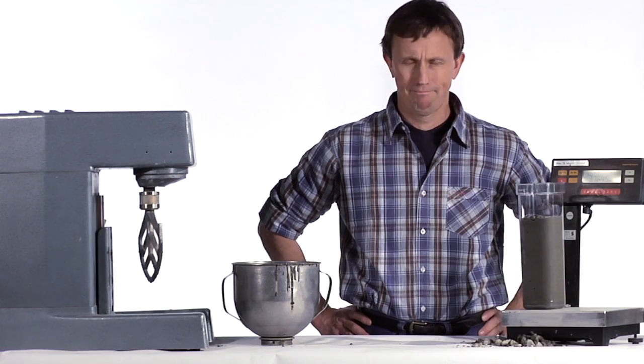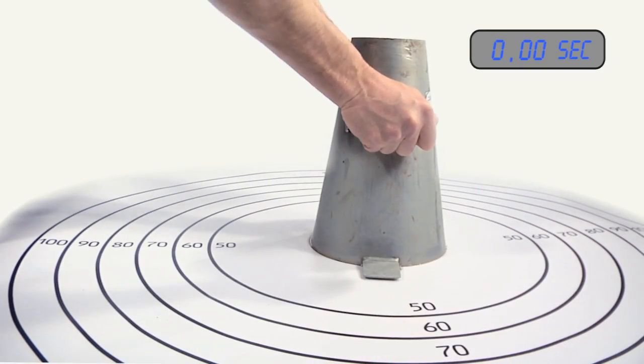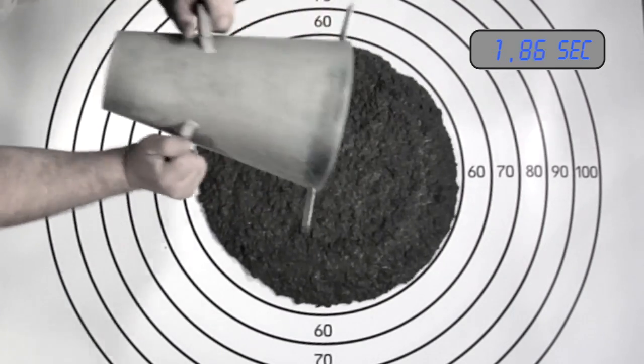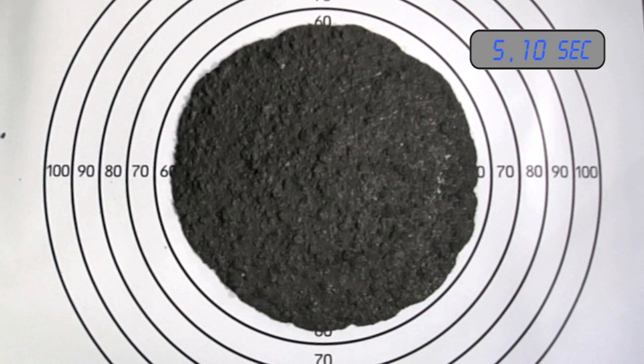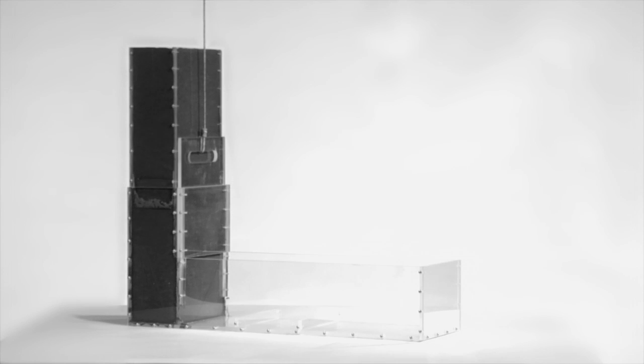To illustrate this, we've taken two additional tests. A flowability test, or the pizza test. 20 liters of concrete, it's regarded to have sufficient flowability if it flows out forming a disc with a diameter of at least 65 cm.